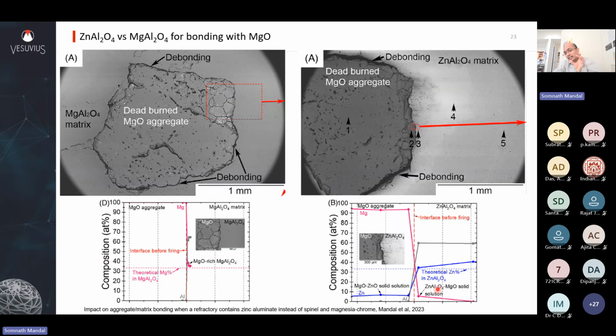All that is happening is ion diffusion across the interfaces, so there is no volume expansion, nowhere close to what happens in an in situ formation. For sure there would be a lattice constant difference between pure zinc aluminate spinel versus magnesia solid solution zinc aluminate, but that is nowhere close to the volume expansion you normally get with in situ magnesium aluminate formation.